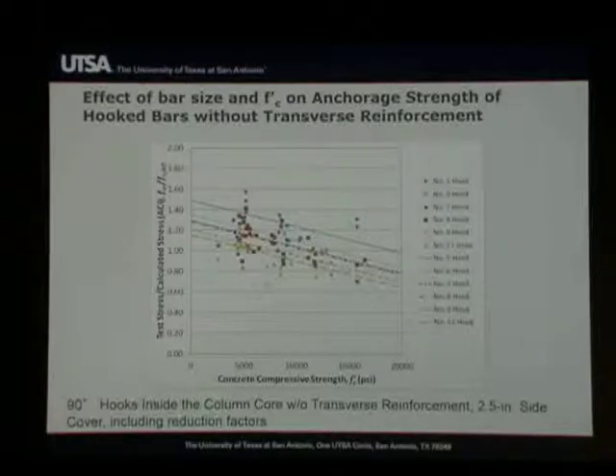The blue line will correspond to number 5 bars, number 6 bars for the lighter blue broken line. Then we'll go 7 and 8, 9 and number 11 bars. And so what we see from this analysis is that the test results are indicating to us that there's definitely different levels of conservatism for different bar sizes.